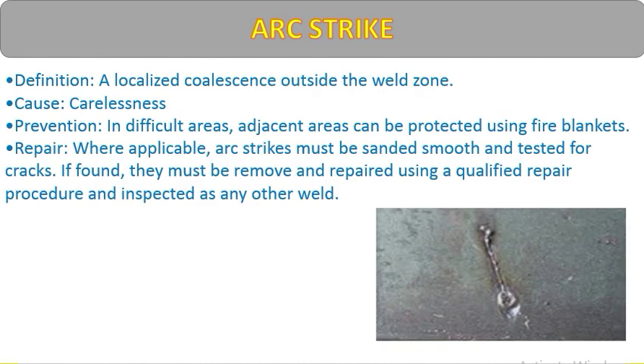Arc strikes are localized areas of damage outside the weld zone. Cause: carelessness. Prevention: adjacent areas can be protected with a fire blanket so arc strikes do not occur outside the weld area. Repair: the arc strike must be ground smooth and tested for cracks using LPT, DPT, or MPT.